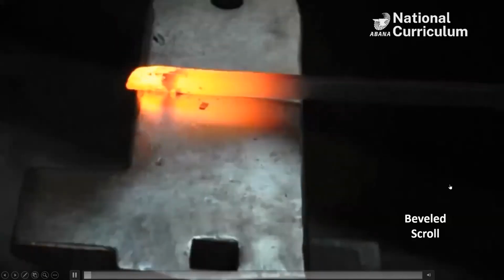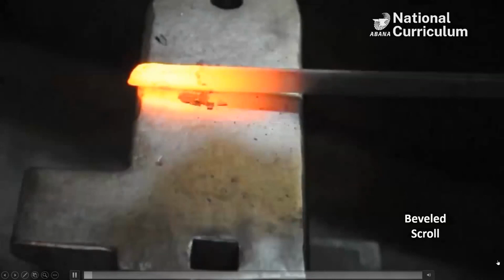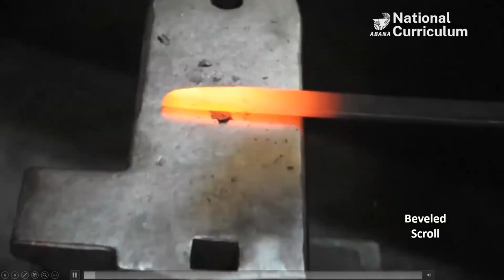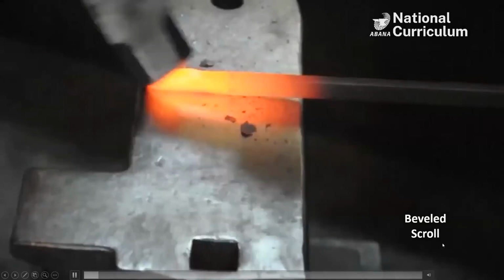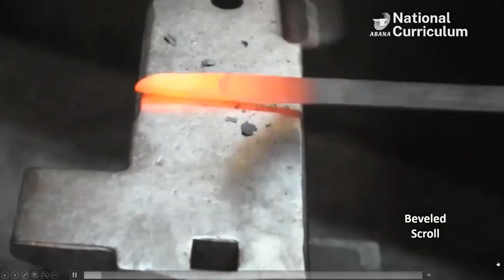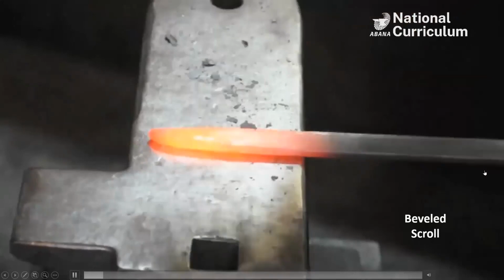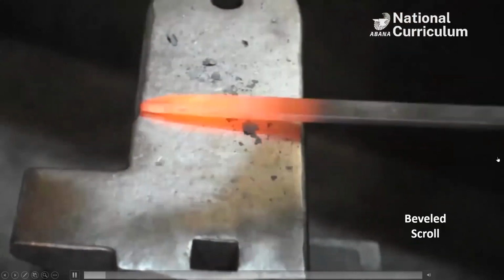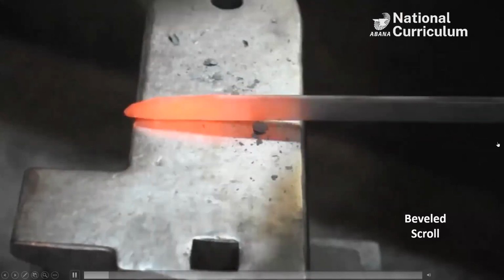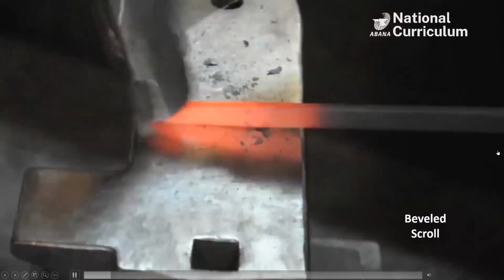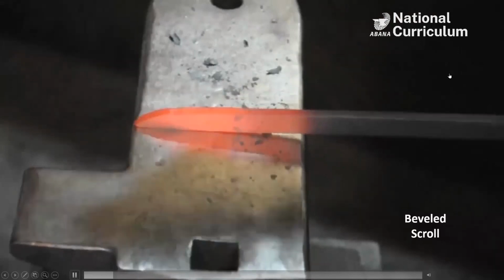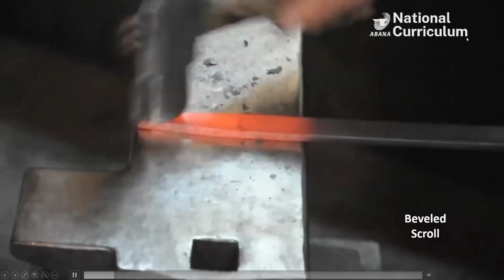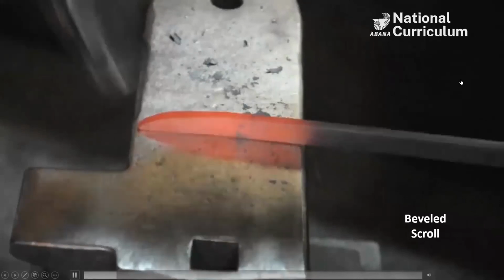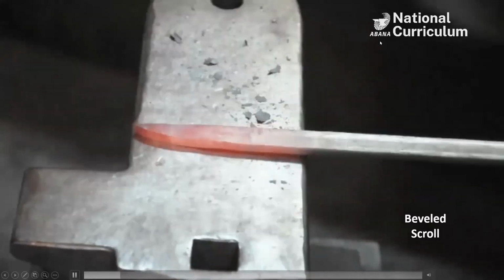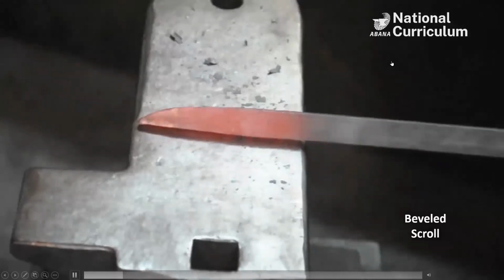Okay, short taper. You really have to start at the very tip, otherwise you don't get it to taper that short, and you need to hit it hard, correct, for the width, for the thickness of the stock, sorry. And try to taper in that one dimension and keep the thickness the same everywhere. There we are. That's about the shape you're going for.